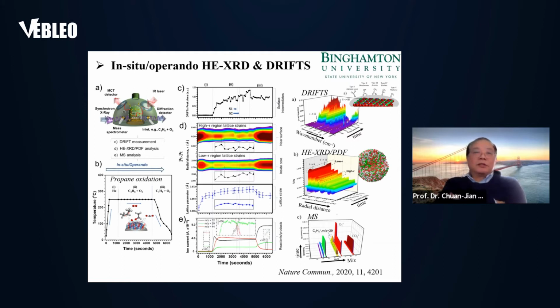In the lower panel, you can detect the product. If you really zoom in to look at the product, you can also see the oscillatory behavior. So really this set of results illustrates the surface site is highly dynamic, and particularly the oscillatory behavior illustrates not only that the surface site is highly dynamic, but its crystal structure is also highly dynamic. Okay, that's really the key point I want to emphasize from this in situ operando study.